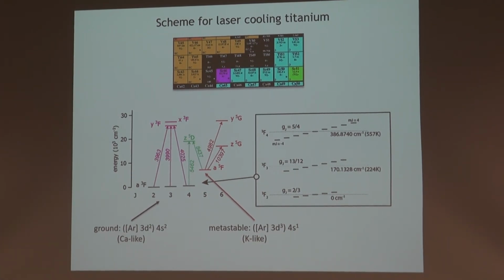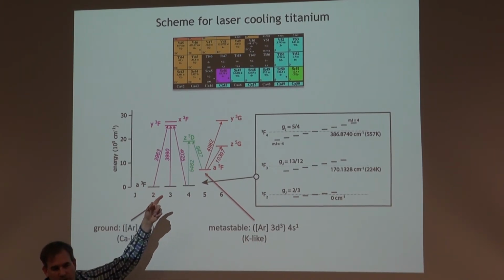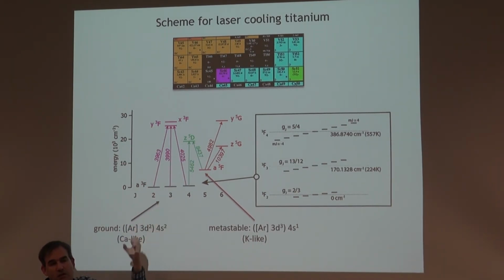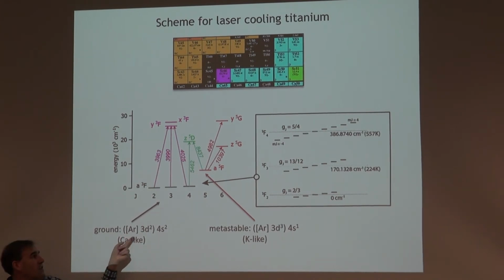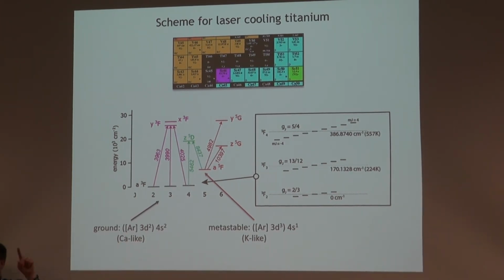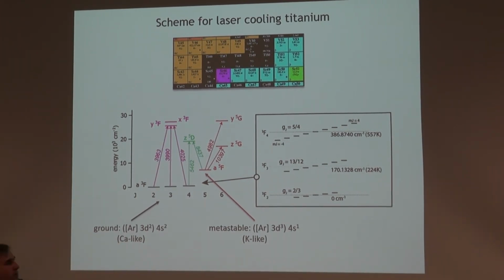But it turns out calcium is really unappealing or unsuccessful for laser cooling, because after you've driven atoms from the 4s to the 4p level, there's often a decay in calcium into the 3d shell, and that leaves calcium in sort of a metastable state, and you have to pump it out of those states so that you don't lose the atom. For us, that would occur in this case as well, so I wouldn't recommend laser cooling out of these ground states. This pumping into the d orbital, though, can work in our favor.